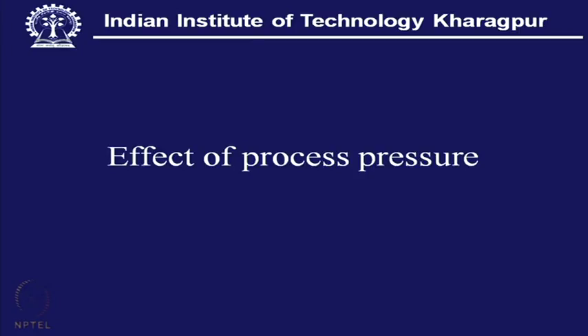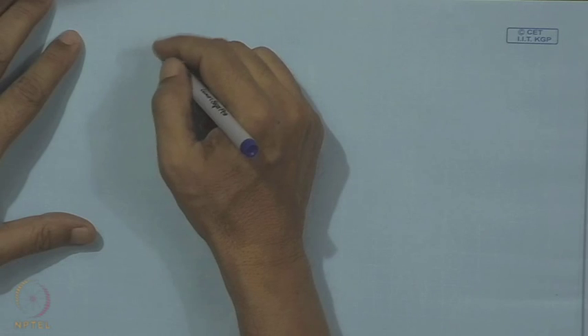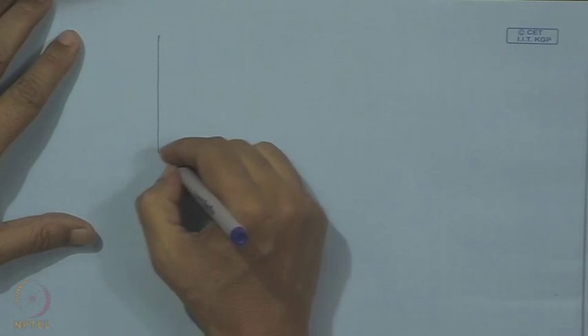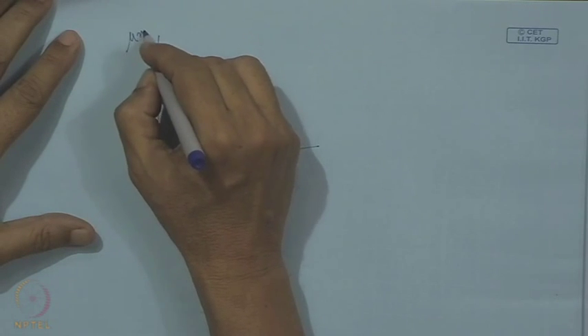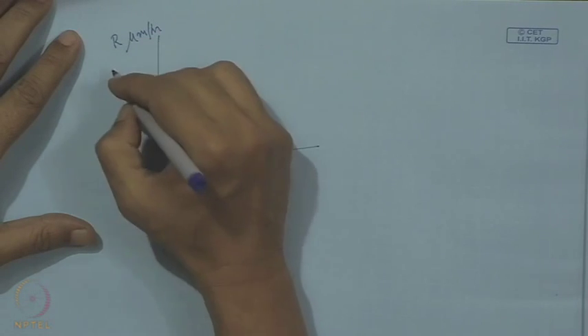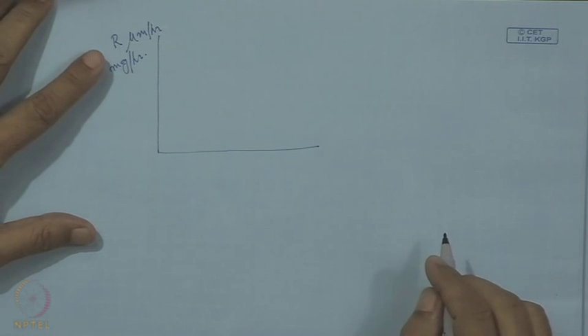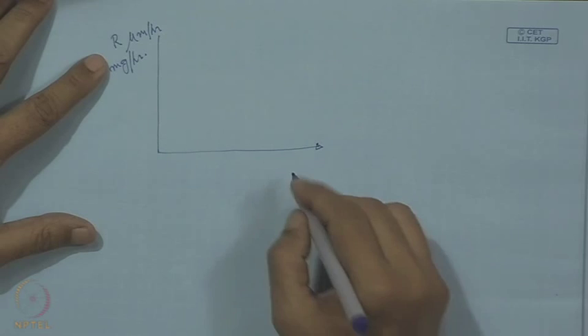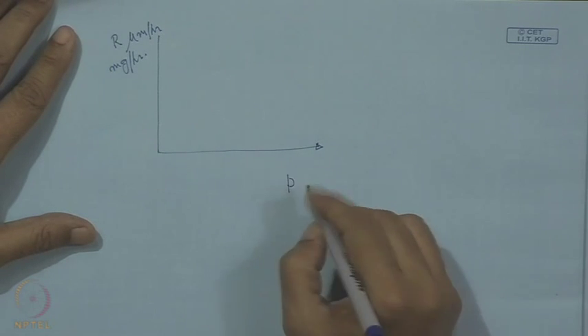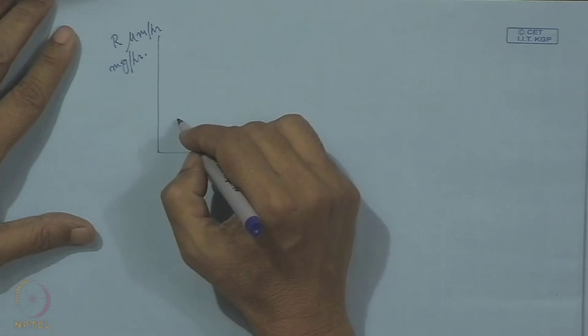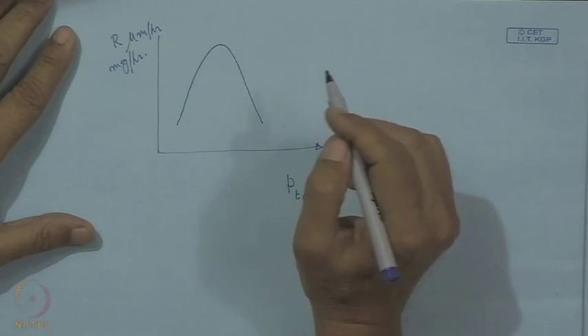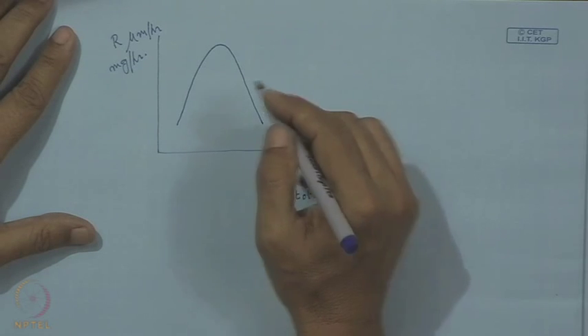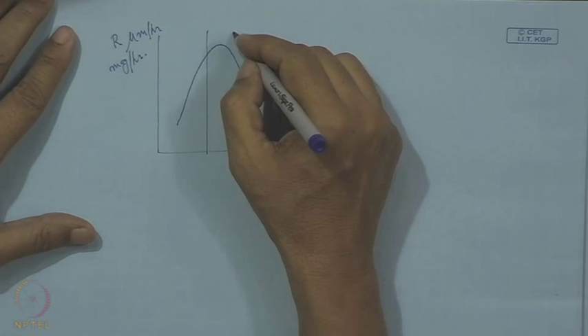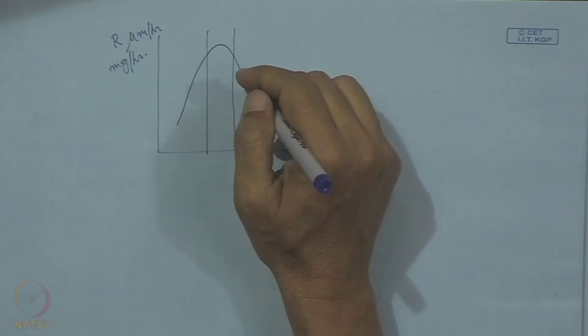This is the effect of total process pressure. On this side, it is the growth rate, which we can express as micron per hour, or it can be just the increase in weight of the substrate in terms of milligram per hour. And this side is the total pressure inside the CVD chamber, and here we may expect a curve something like this. Now, we can interpret this curve in this form: this is an interesting zone for conducting the CVD operation. Now, why is it so?